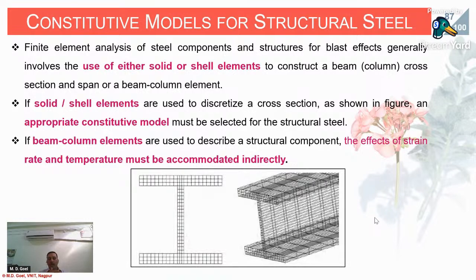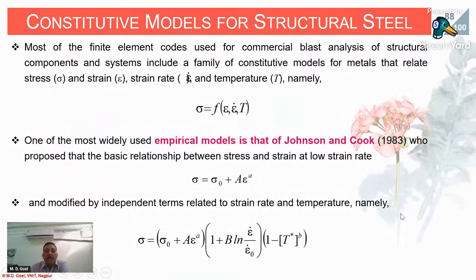So combining all these things can be achieved by doing some tests using either SHPB or shock tube and developing such kind of relationships. This is a very important relationship, particularly for structural steel, which is called the Johnson-Cook material model: sigma equals sigma 0 plus A epsilon raised to power n, times 1 plus B ln of epsilon dot upon epsilon 0 dot, times 1 minus T raised to power m.